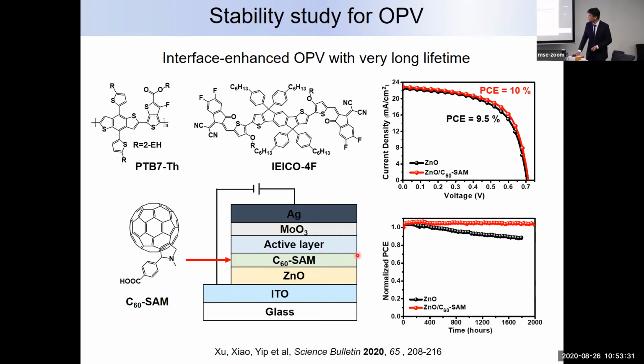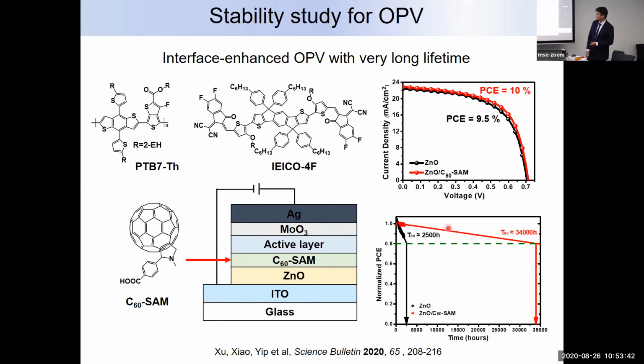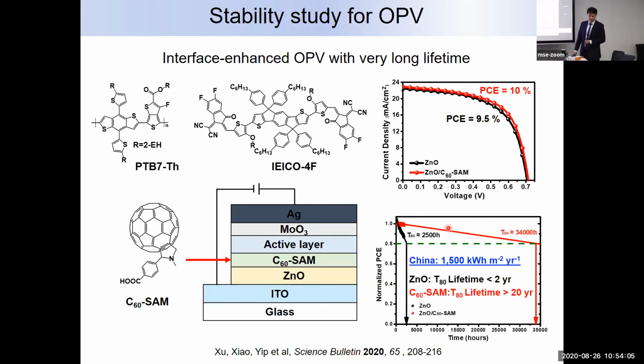So what we found is that when we introduced this C60-SAM, compared to the one with pure zinc oxide, the stability further improved. It's highly stable, okay? And of course, when we're trying to extend the stability, we use this T80 lifetime, which means from the original efficiency going down to 80% of the efficiency, how long it takes. And this SAM-modified device has a lifetime of up to 34,000 hours, which means if we consider every year we only have 1,500 hours of sunlight, this can be 20 years of lifetime.